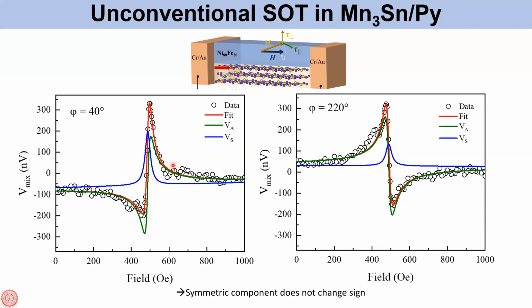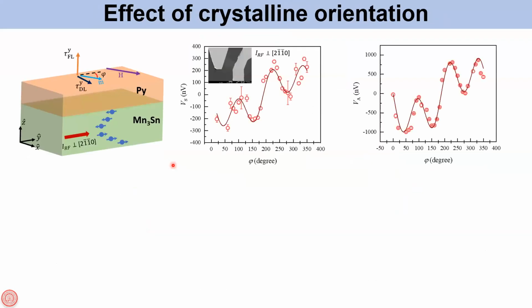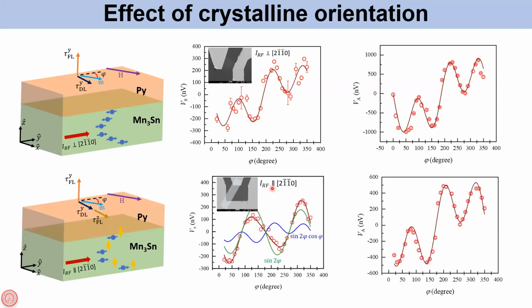In order to understand the origin of this unconventional spin orbit torque, we tried passing RF current in different crystallographic directions of Mn3Sn, because Mn3Sn in our case is epitaxial. Here the RF current is perpendicular to this particular in-plane direction, and we see that the torque is conventional because both the symmetric and antisymmetric components follow the sin 2 phi cos phi dependence. But if you pass a current at 90 degrees, or parallel to this particular direction, then we start to see unconventional torque because the symmetric component no longer follows the sin 2 phi cos phi dependence. So this is an indication that this unconventional torque in this system is coming from the crystalline structure of this Mn3Sn.